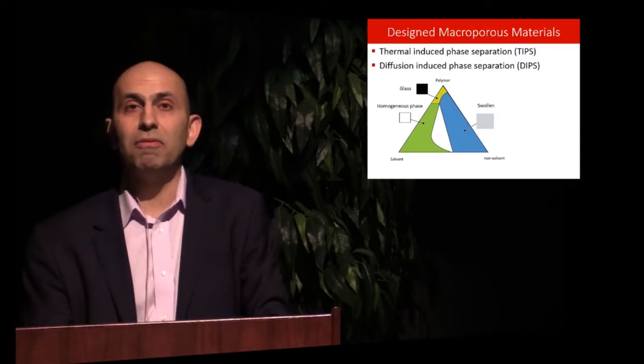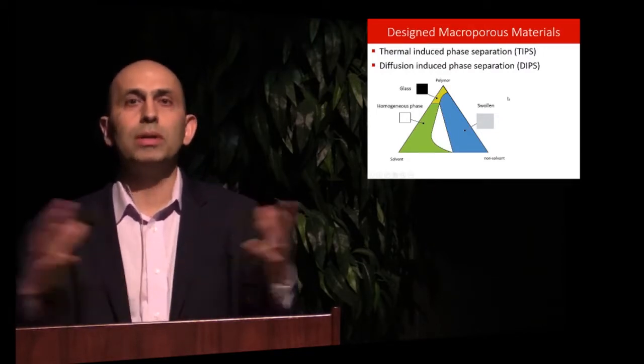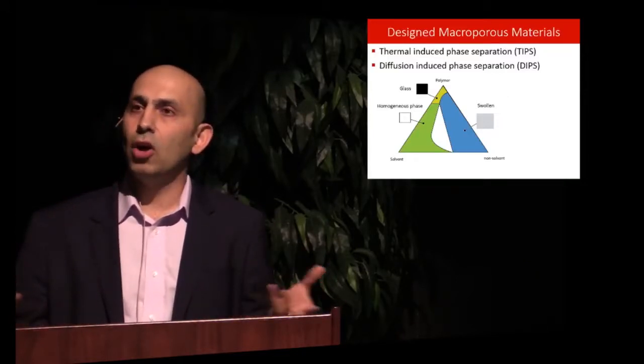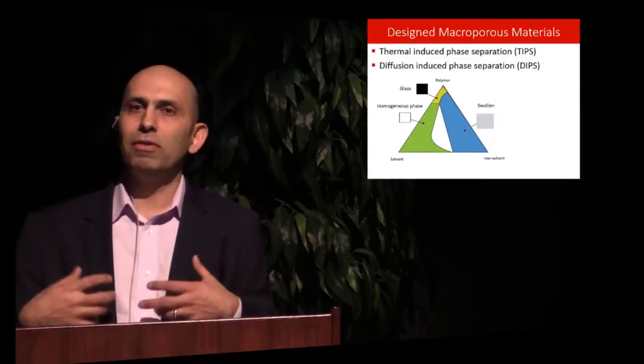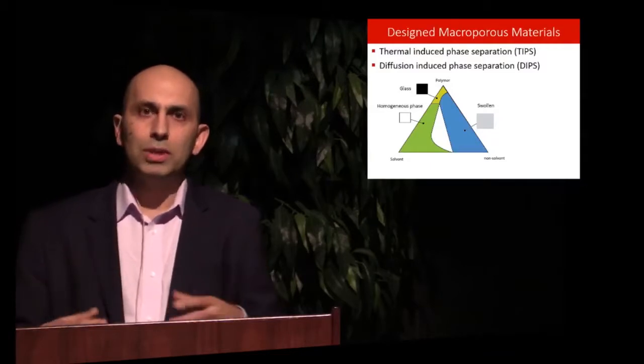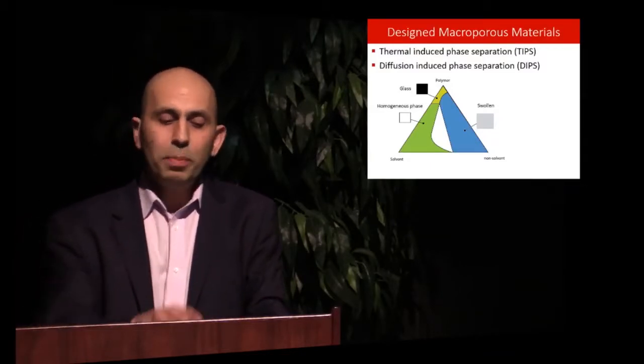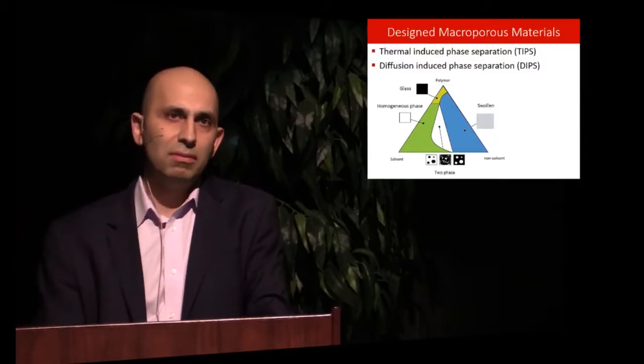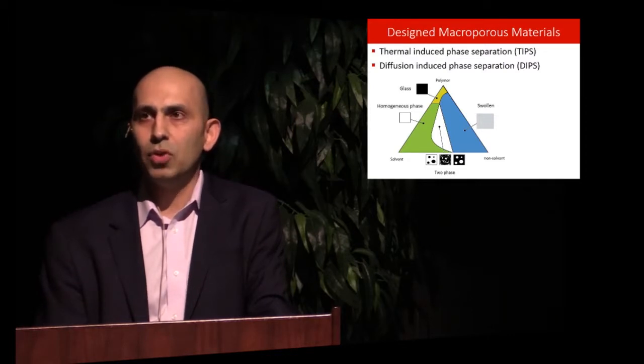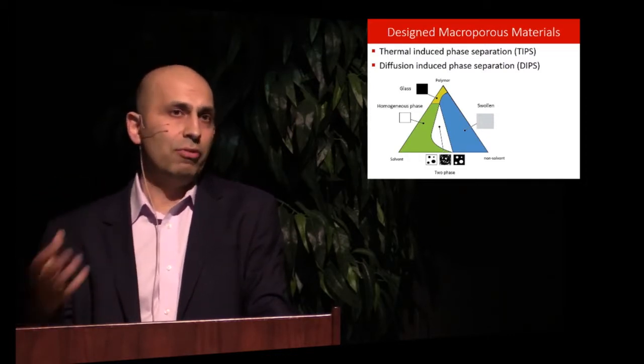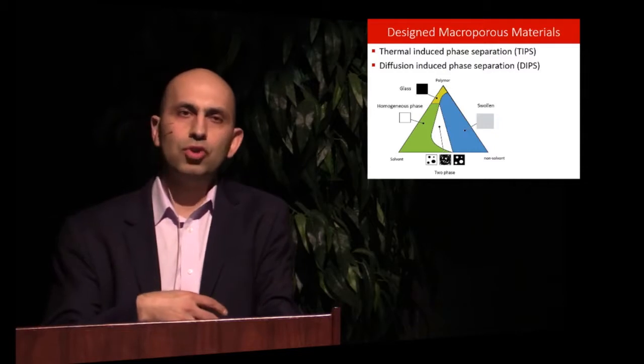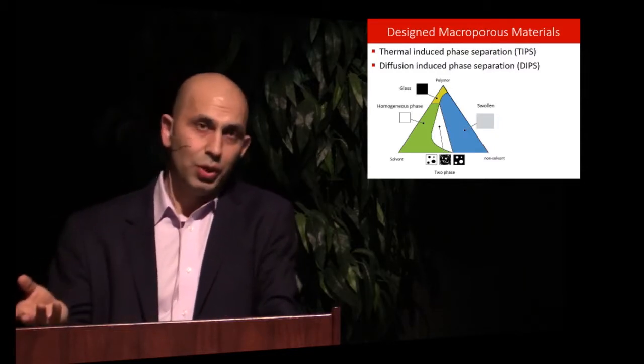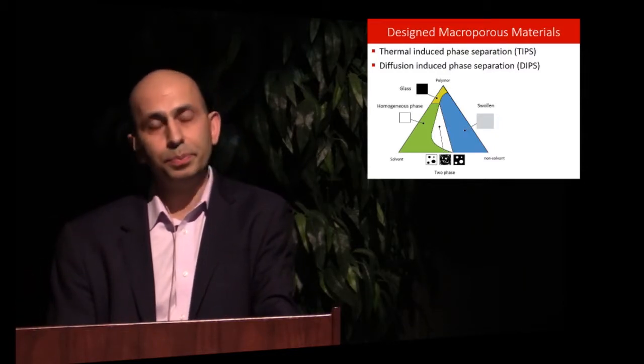As a result, we end up with a swelling situation. The polymer swells because it is a significantly large molecule and can take in solvent and non-solvent molecules. And there are domains in which two-phase properties show up. So we have domains which are rich in polymers, and domains which are poor, or do not possess enough polymeric material.